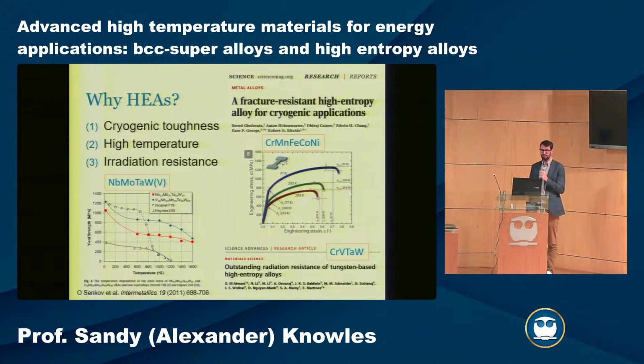So particularly this system, chromium, manganese, iron, cobalt, nickel, on the right-hand side, has shown almost the best combination of strength and ductility at cryogenic temperatures of any material that's known. And from that, we have a new design logic as to how to design materials for cryogenic applications.